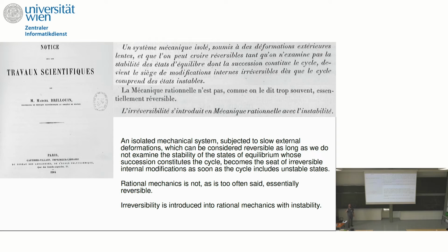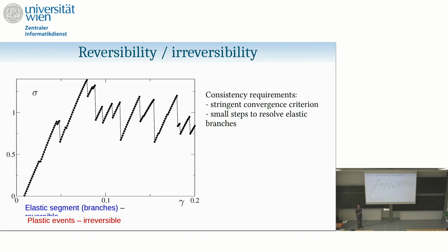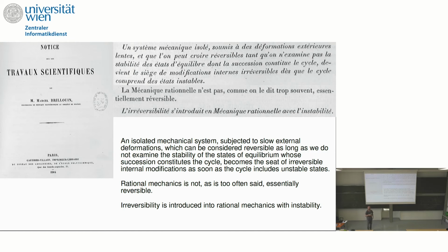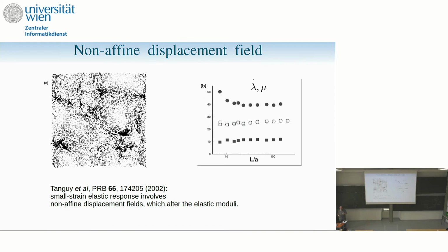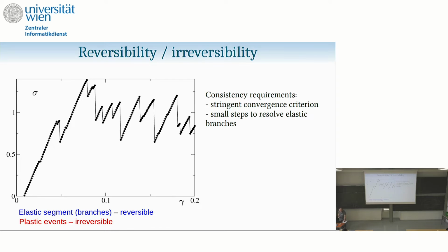This is just completely amazing, that they were deducing this. And essentially, irreversibility is introduced in rational mechanics with instability. That's exactly the point I want to make: dissipation in a perfect plastic flow is strictly the consequence of mechanical instability, and it's completely controlled by mechanical instability. Okay? Of course, we need to understand this instability a bit better. So before we go down, we have these branches and events. We will look in some detail first at the elastic response and then at the plastic response.